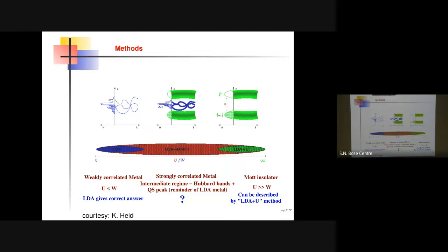So different techniques as a function of U over W. If it is small, we are pretty good with doing the LDA. You have very well-defined bands, and you have the density of states. Even in the other limit, very strong correlation, you repair the LDA by doing some LDA plus U calculation, that has not been mentioned in this conference at all, but you can do that. In that way, a gap opens because of the effect of U, and the thing becomes completely localized. You have a lower Hubbard band and an upper Hubbard band.